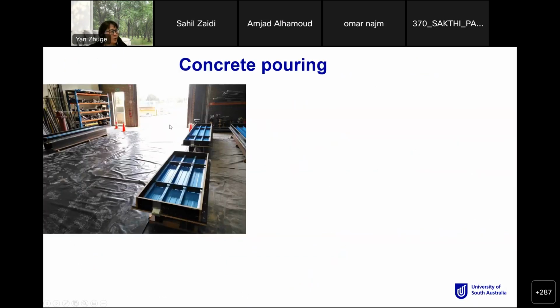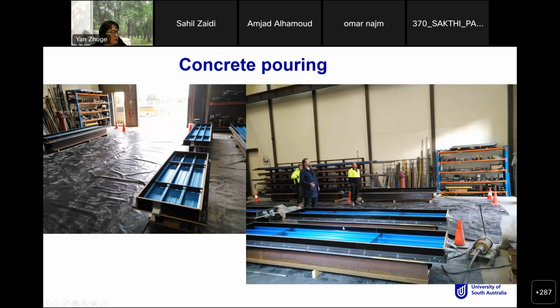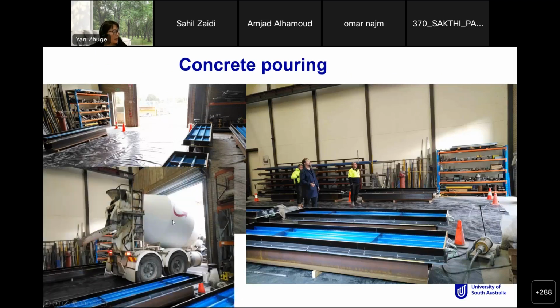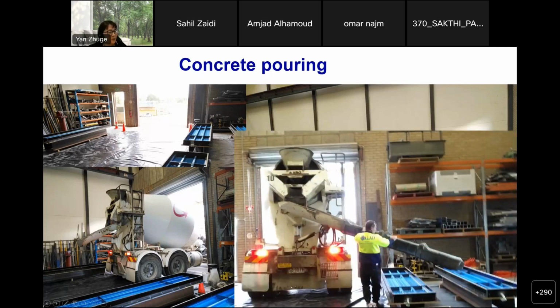So that is the actual construction of this composite slab. That is before the concrete pouring. So we just had the formwork ready and got the formwork all set up. And then we got a concrete truck because we tried to simulate a real construction situation. So we didn't do any laboratory mixing. We got a construction company who does normal, real, practical concrete mix deliveries. And we asked them to pre-mix the crumb rubber concrete for us based on our mix designs and deliver it to our laboratory, and that is the pouring of these concrete slabs.